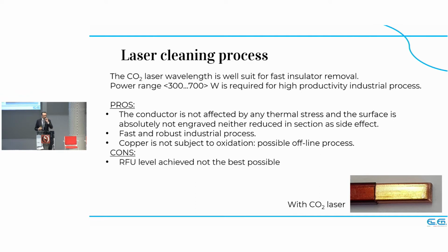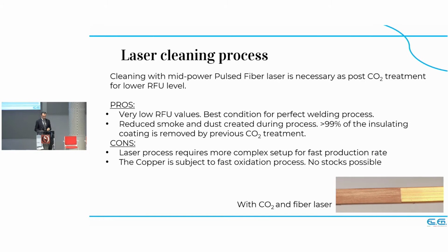Given the fact that CO2 leaves this micron of material, the copper that is cleaned by CO2 doesn't oxidize, because we still have this tiny protection. Obviously, this can also be a disadvantage because we still have these little contaminants on the surface that we can test with a few instruments. So in order to provide a fully clean surface, we have coupled CO2 with a mid-power pulsed fiber laser. We don't need too much power with the fiber laser, but we still need it in order to get rid of this very tiny insulant left.